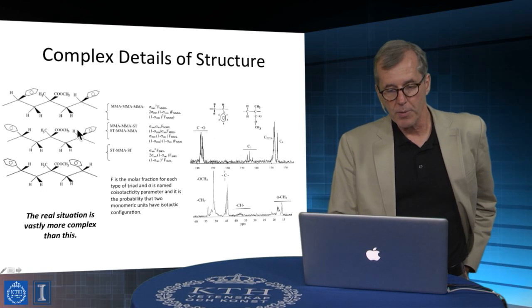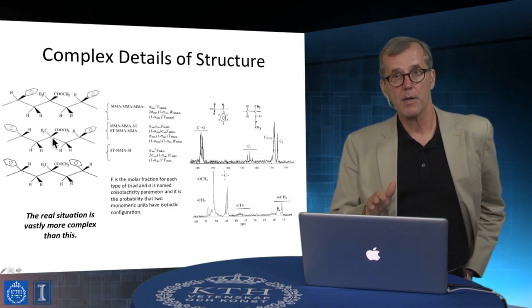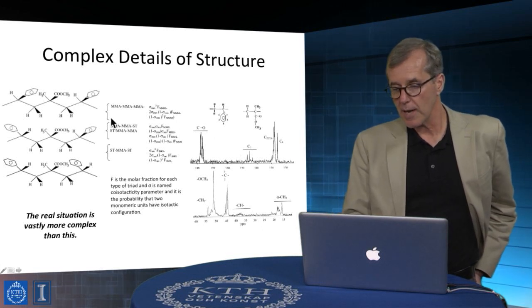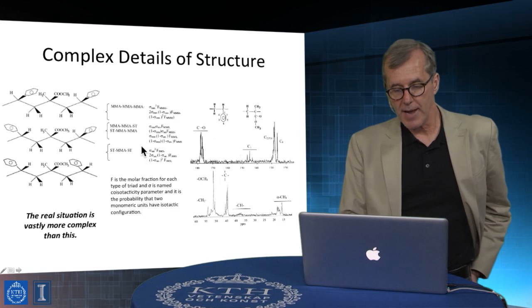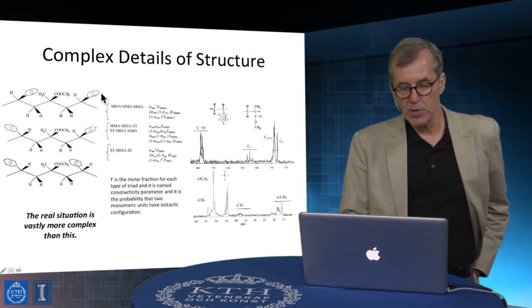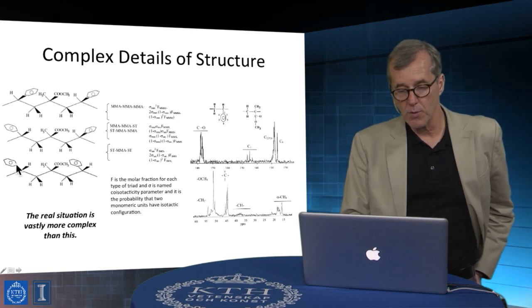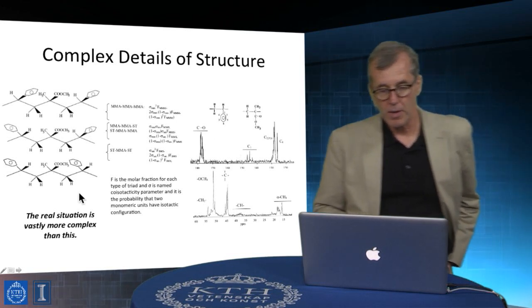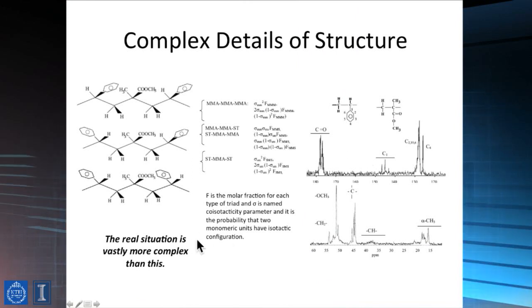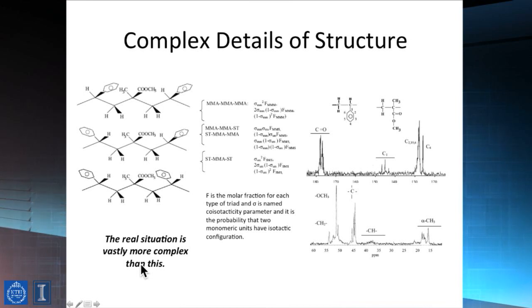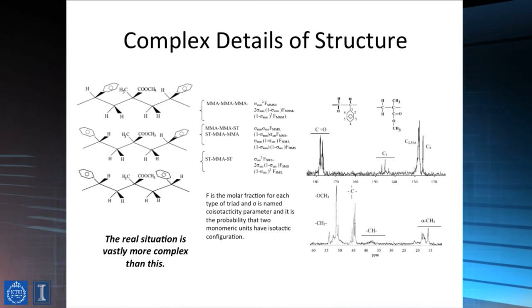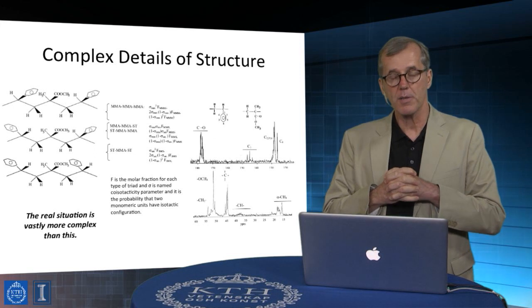And it turns out that all the couplings in this particular case can be fundamentally analyzed in depth and the assignments made to say what the average tacticities and probabilities are for finding sequences of any one of these forms, as shown in the schematic depiction. The real situation is a little bit more complex than what I've shown. I tried to simplify this into so-called triad sequences, and you could look further out, pentads or whatever, and that sort of level of analysis can be done. However, it typically requires a little bit of expertise in NMR spectroscopy.